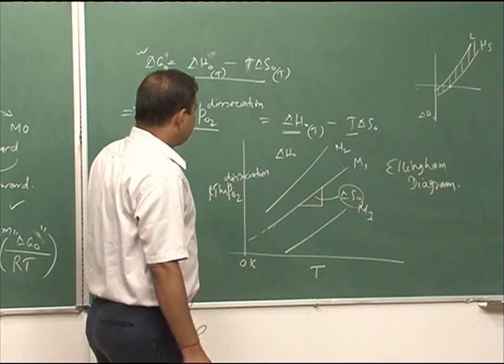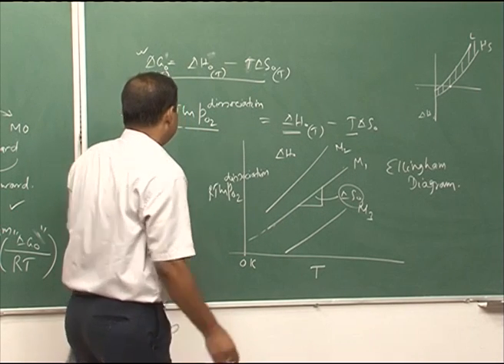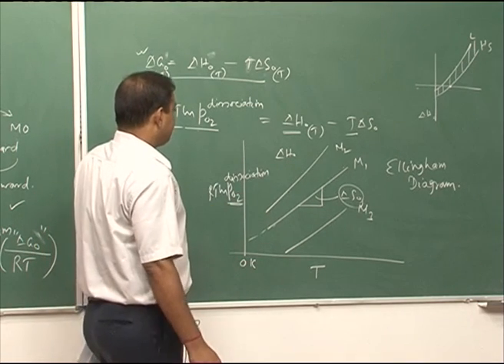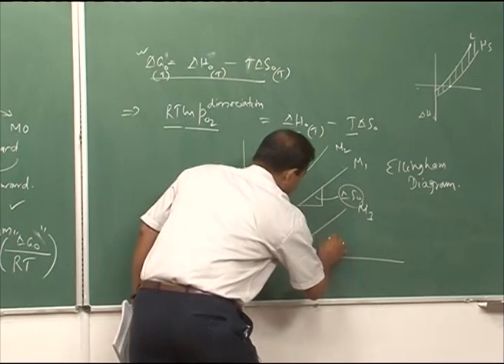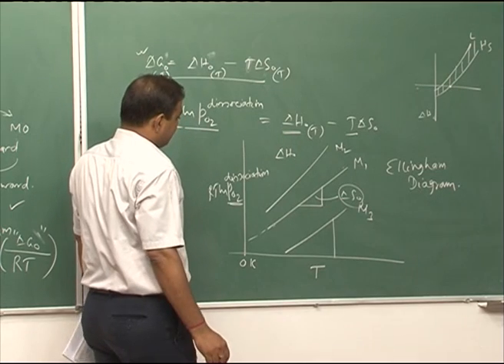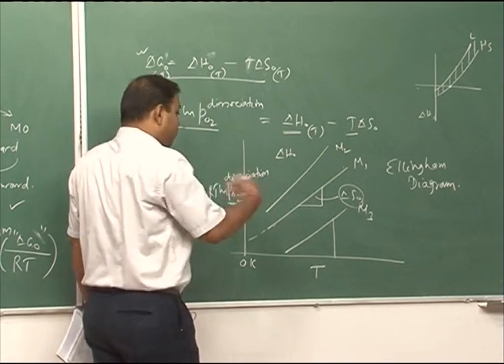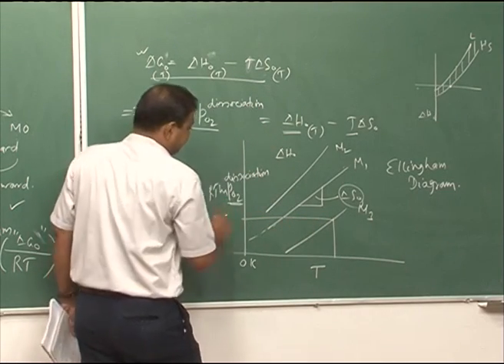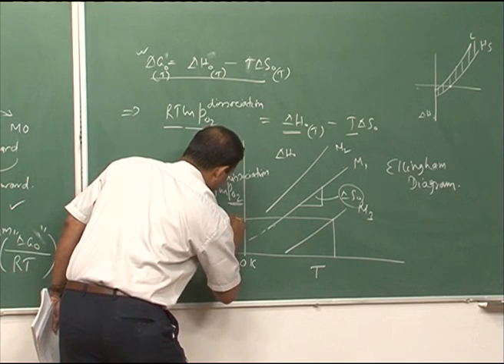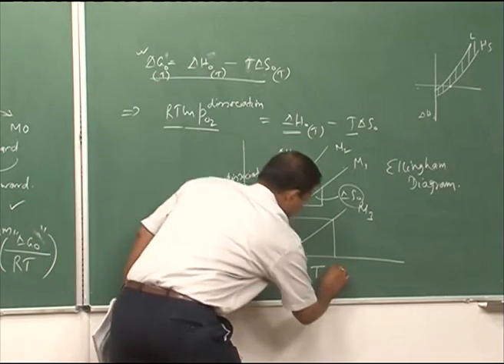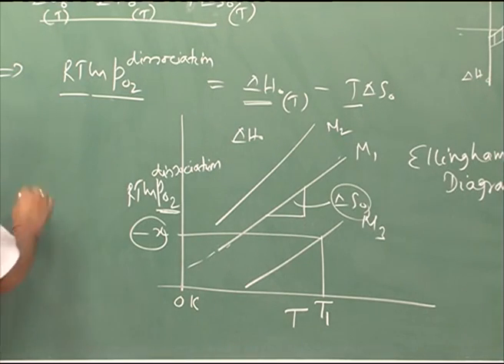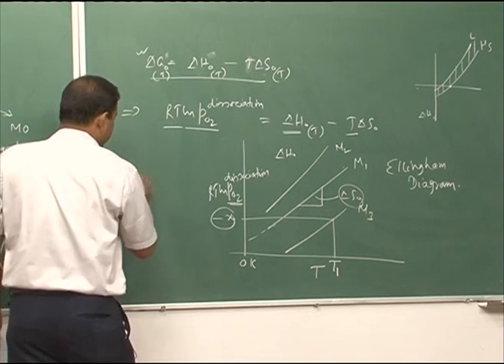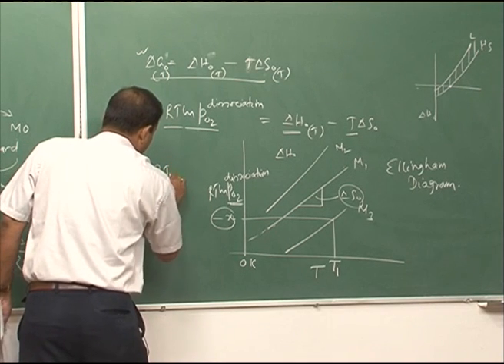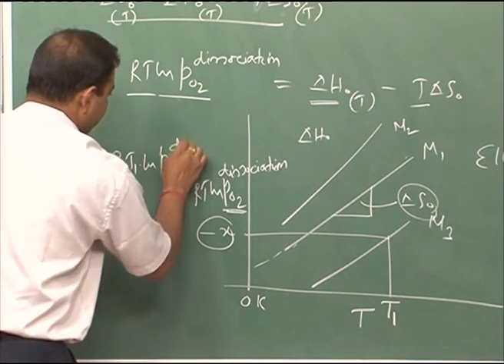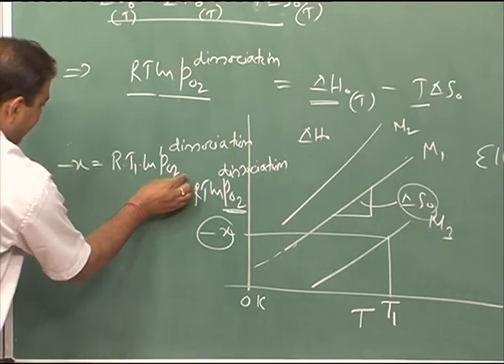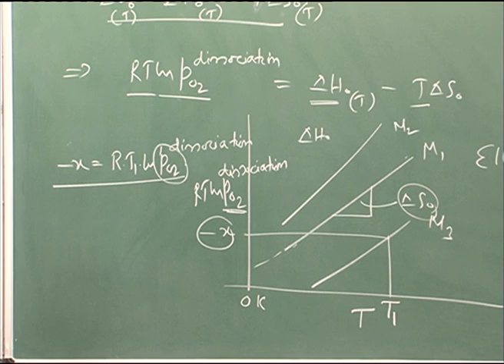So, the Ellingham diagram would give you an idea of what the dissociation pressure of oxygen would be at different temperatures for the formation of an oxide or for the dissociation of the oxide. Now, let us say I would like to find the dissociation pressure of oxygen for that particular oxide. Let us say this value is minus x, and the temperature is T1. Now, we can find the dissociation pressure of oxygen. So, minus x equal to R T1 ln PO2 dissociation, and from this we can find the PO2 dissociation pressure.